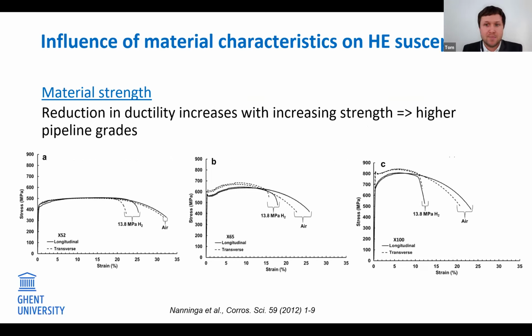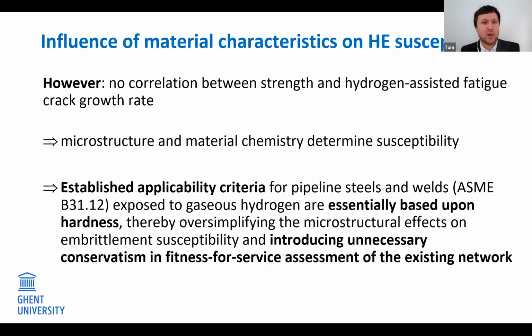And also currently, the standardized acceptance criteria for pipeline steels and their welds in hydrogen application, which is the code ASME B31.12, are based on the maximum allowable hardness of the pipeline material. So there you can see the link with the strength level and the hardness. However, when going through the literature, this is somewhat contradictory, but generally, the literature fails to confirm a correlation between the strength and the hydrogen-assisted fatigue crack growth for pipeline steels.